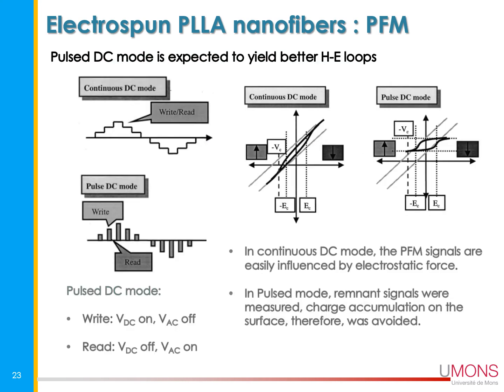Another important point before going to the data is that if you want to generate those shape, amplitude, and phase that we saw before, we have different modes, either the continuous DC mode or the pulse DC mode. The problem with the continuous DC mode is that you are influenced by the electrostatic force, which is not what you want to measure. You want to measure the pure piezoelectric properties.